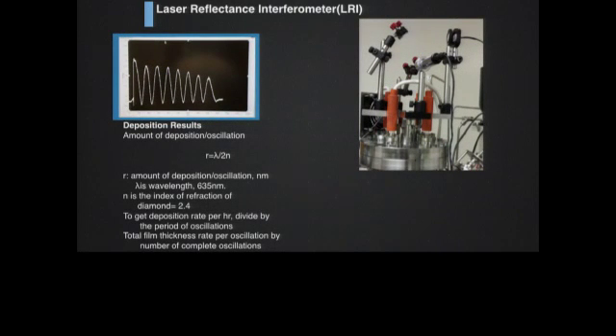So I just put this on here. This is the laser interferometer. Basically, we point it at the surface, and of course you get destructive and constructive interference. If you know the wavelength of the laser and the index of refraction of the material, you can actually in situ measure the thickness of the layer, and this is each one of these layers as they're growing, during the actual growth process.